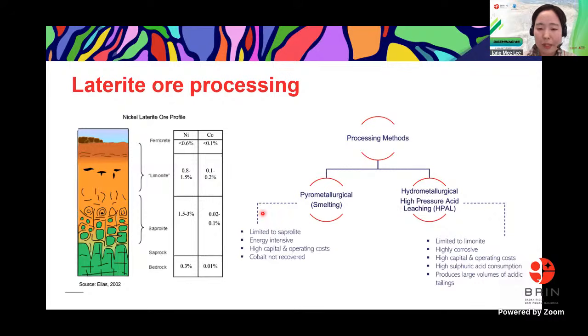Saprolite ores are commonly processed with the pyrometallurgical route, such as smelting. But these processes are highly energy intensive and require significant capital investment, and sometimes do not efficiently recover the cobalt. On the other hand, limonite ores are generally treated using a hydrometallurgical pathway, like high pressure acid leaching, HPAL. It's really effective in extraction of nickel and cobalt, but HPAL operates under highly corrosive conditions. It requires substantial sulfuric acid consumption and generates large volumes of acidic tailings and neutralization sludges.